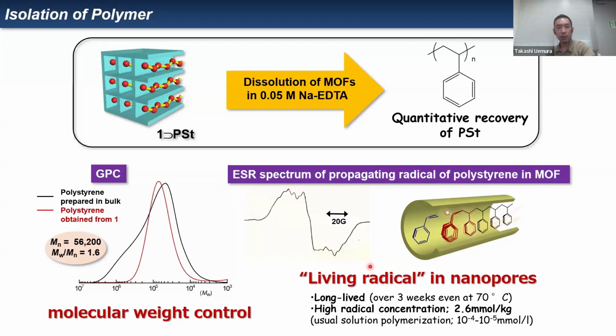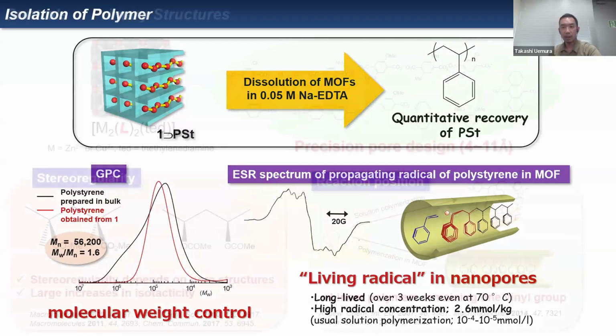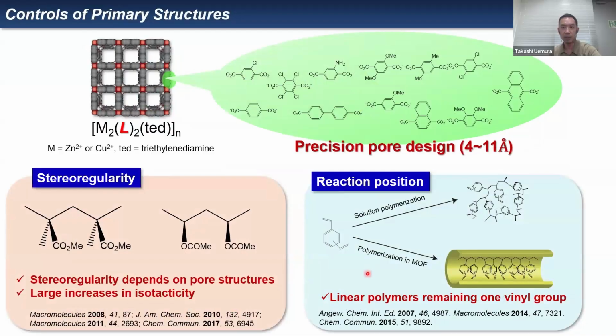Okay. So now we could obtain the polymers from this composite. So next, in this framework, we can control the pore size and shape by changing a ligand. And then we could perform the polymerization using these pores. So actually, stereoregularity of the resulting polymers can be finely controlled depending on the pore structures. And when we carry out the polymerization of this type of divinyl monomers, we could obtain linear polymers, remaining one vinyl group like this. So this type of polymerization has never been attained before, because to recognize these two vinyl groups is impossible in the previous polymerization. But this channel could direct the polymerization in a 1D fashion.